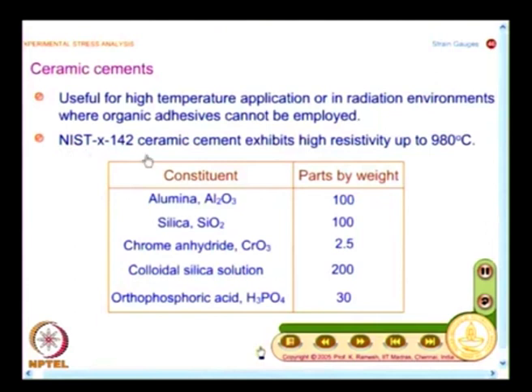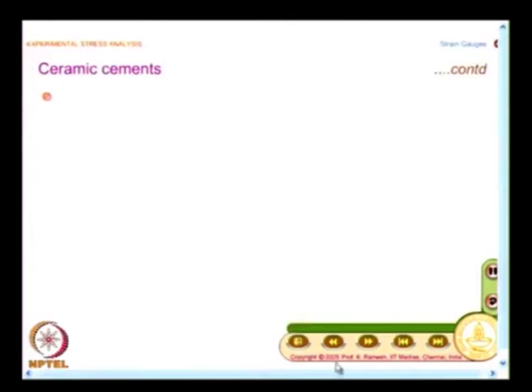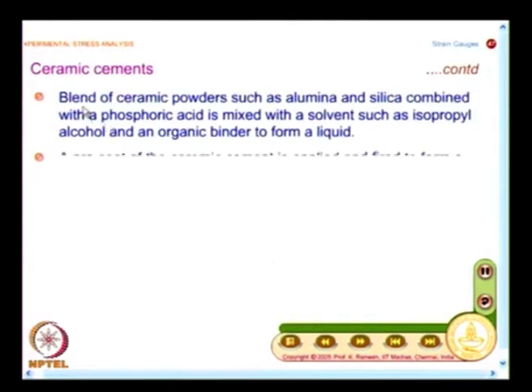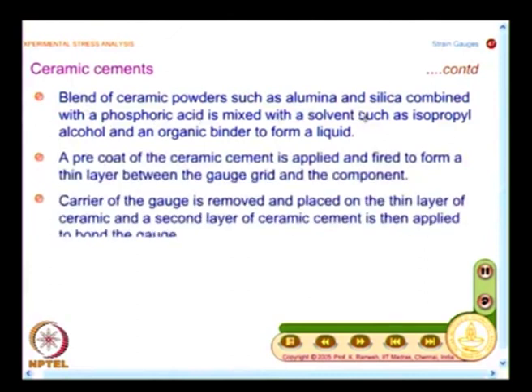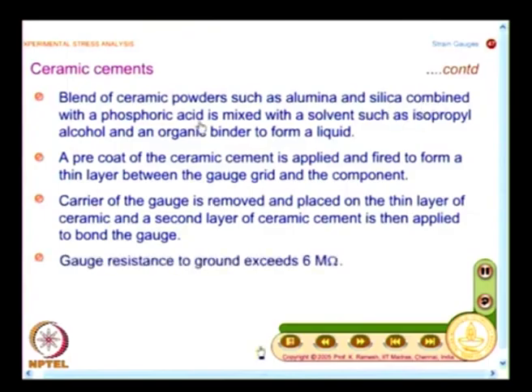And what you have here is the constituents of NIST X142 is listed here. You have alumina, you have silica, you have chrome anhydride, and you have a colloidal silica solution, and you also have orthophosphoric acid. So, what you have here is the blend of ceramic powders such as alumina and silica combined with the phosphoric acid is mixed with a solvent such as isopropyl alcohol and an organic binder to form a liquid. So, essentially you have this ceramic available as a liquid, so that it is easy for you to apply it by a spraying process.